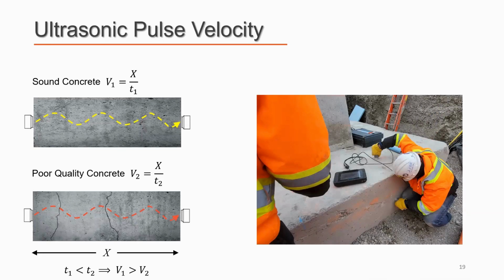Now, if we do have cracks or defects in concrete, we expect that the arrival time of the signal becomes longer. So it means that a poor quality concrete should have a lower pulse velocity. And this gives us a very good benchmark to classify concrete materials.